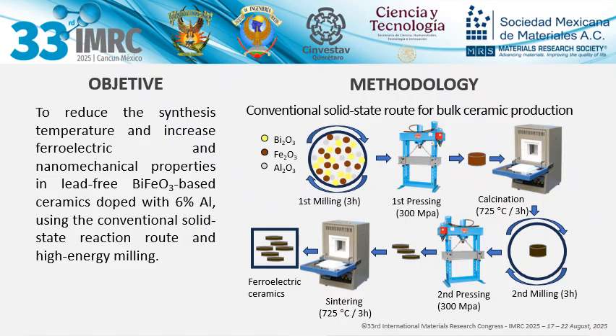The obtained samples were characterized structurally by X-ray diffraction with Rietveld refinement, morphologically by scanning electron microscopy, ferroelectrically through polarization-electric field hysteresis loops, and mechanically via nanoindentation to determine hardness and elastic modulus.